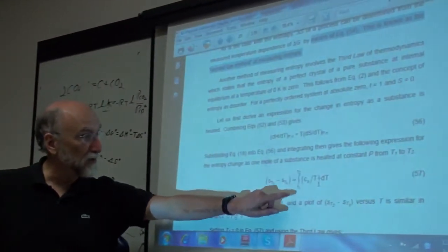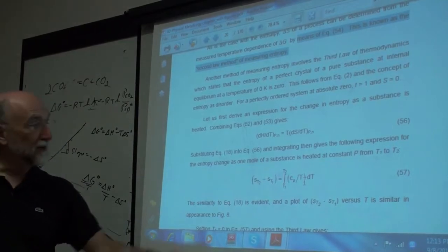Let us first derive an expression for the change in entropy as a substance is heated. Combining equations 52 and 53, dH/dT is Cp, and you can find that dH/dT is T dS/dT. Look back at equations 52 and 53 and convince yourself of that fact. And so the entropy change for heating a substance from T1 to T2 is the integral of Cp over T dT. Remember the enthalpy change, H(T2) minus H(T1), is the integral of Cp dT. The entropy change is the integral of Cp over T dT.